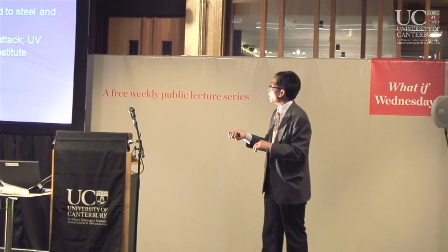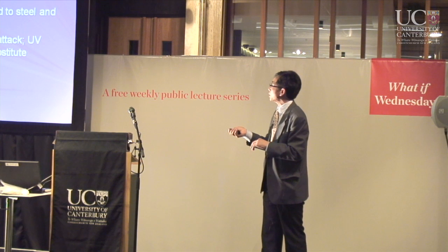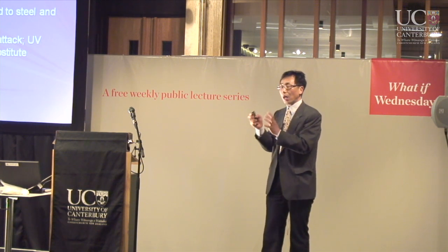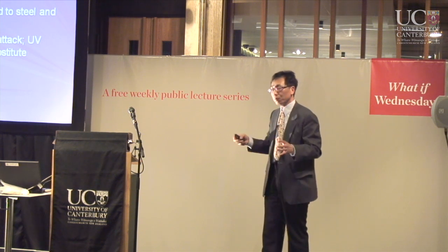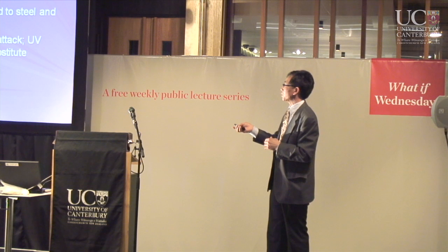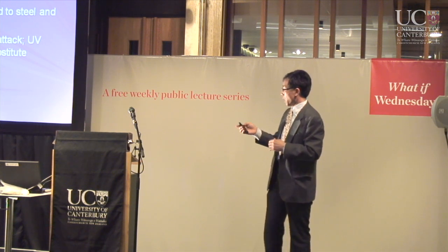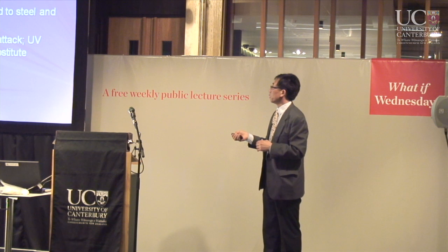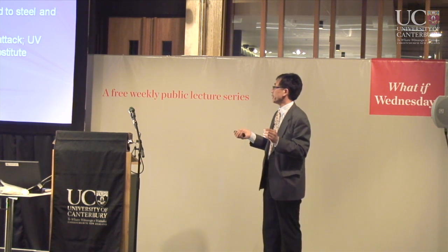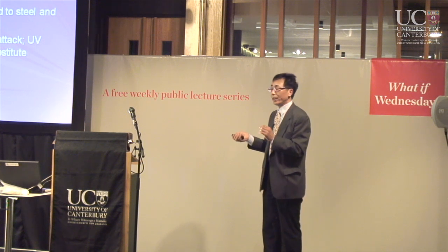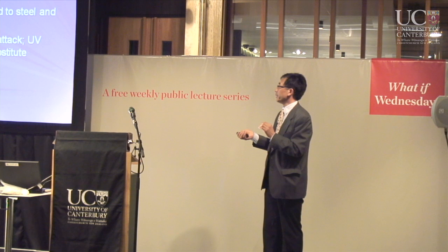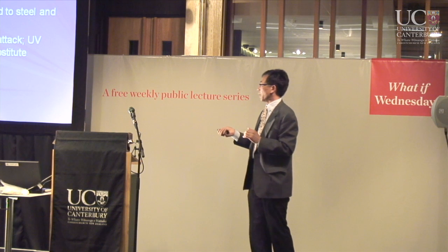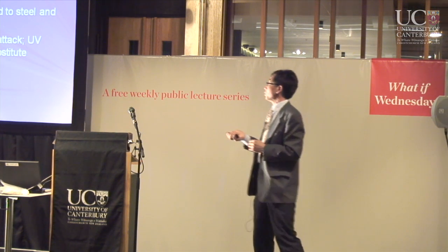And it has a lower weight to strength ratio, that means if you've got this high strength, you don't need too much material compared to steel and concrete. And it is durable compared to wood: anti-insect attack, UV resistant, and anti-decay. It can be used to substitute the chemically treated wood. So that is a good thing.